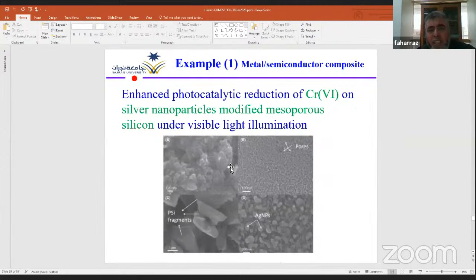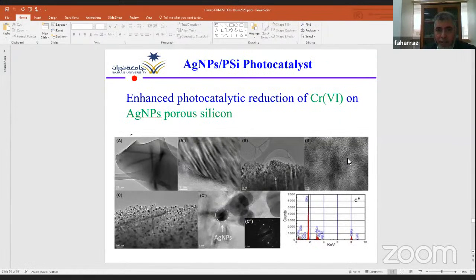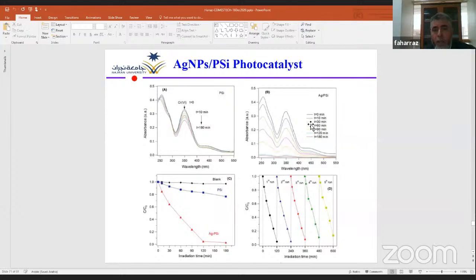I will give you a very brief two examples of our running or published work in this area of photocatalysis. The first example is a metal semiconductor composite. We modified mesoporous silicon with silver nanoparticles and used this hybrid structure for the photocatalytic reduction of chromium-6, a toxic form, to the less toxic or safe chromium-3 under visible light illumination. This is the scanning electron micrograph of porous silicon alone and the porous silicon after deposition of silver nanoparticles. This is a TEM micrograph of our silver nanoparticle porous silicon photocatalyst with some EDX analysis.